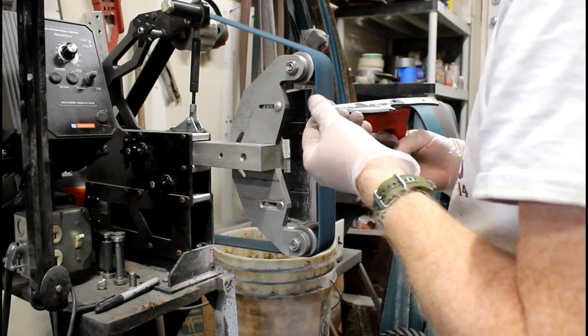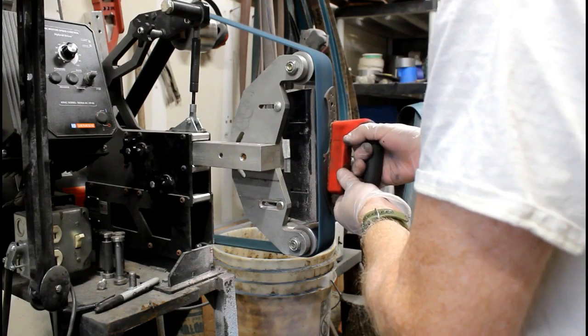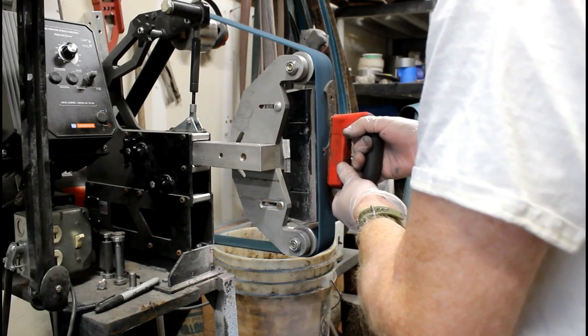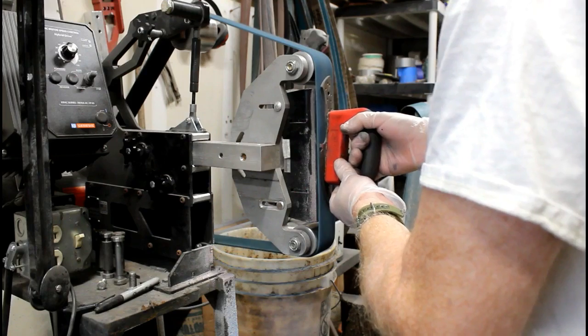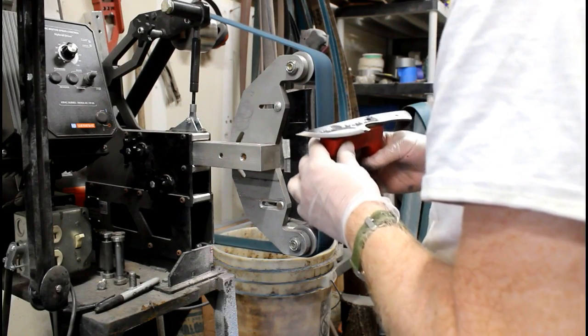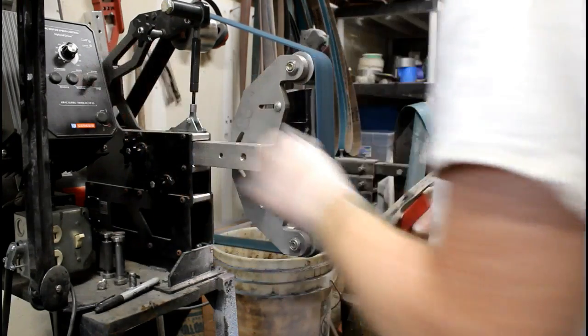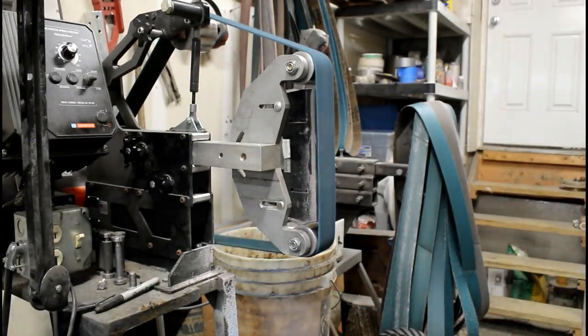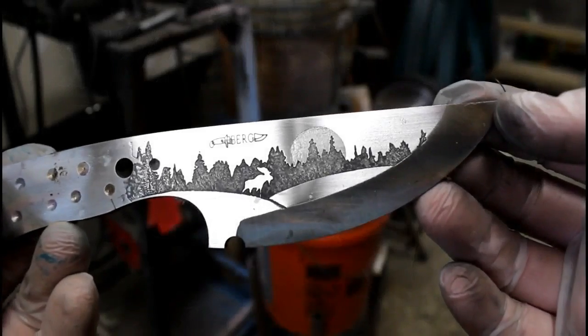Now I found with stainless steel there's absolutely no benefit to doing the etching prior to heat treating. On high carbon steel I always etch prior to heat treating because the background would end up getting much darker. But for stainless steel you don't get that benefit, so I'm etching actually after the heat treating.